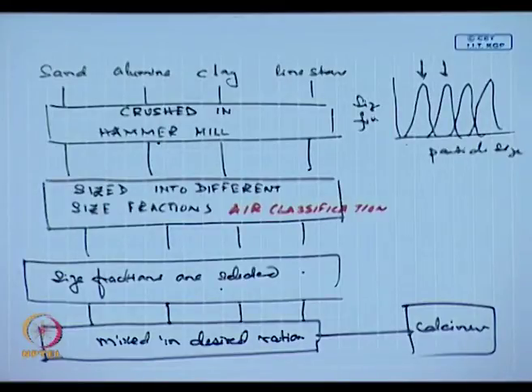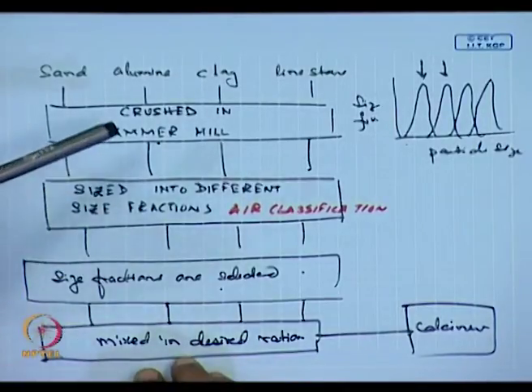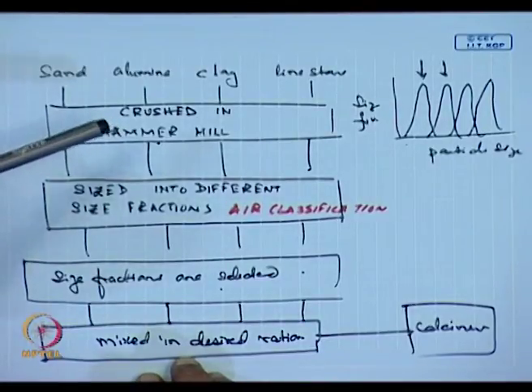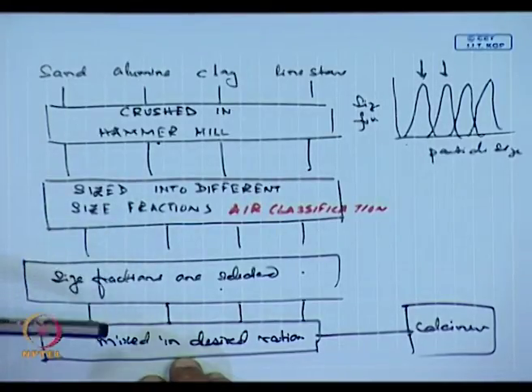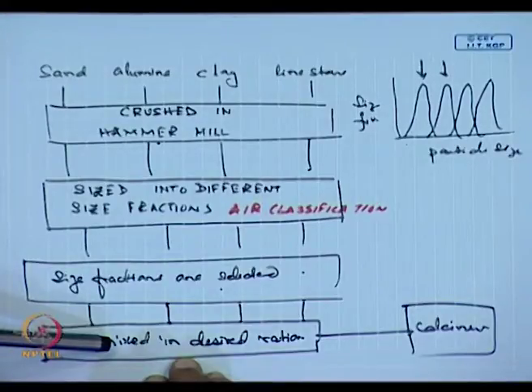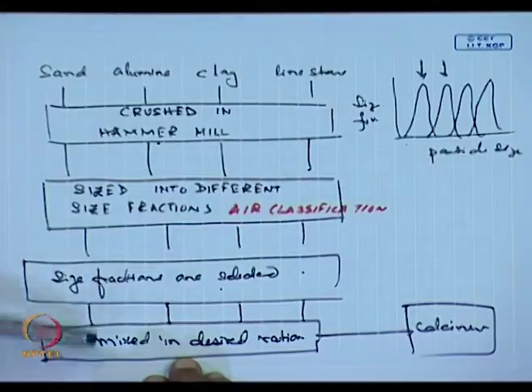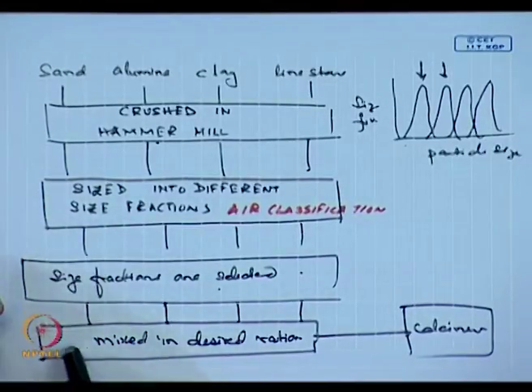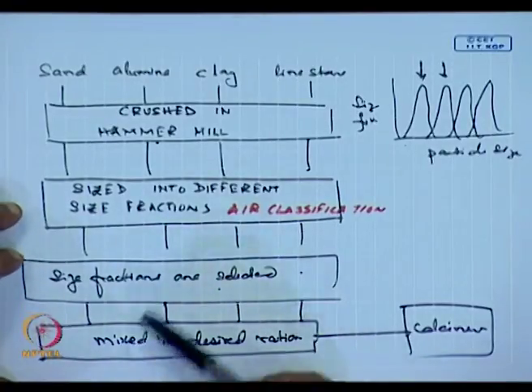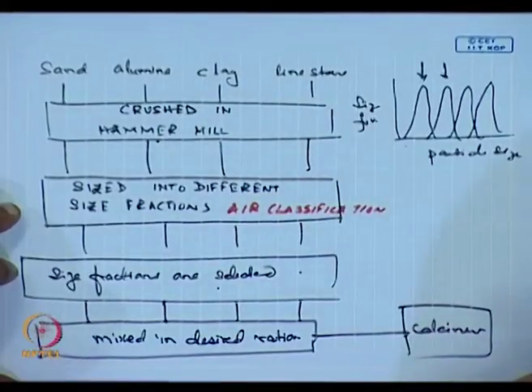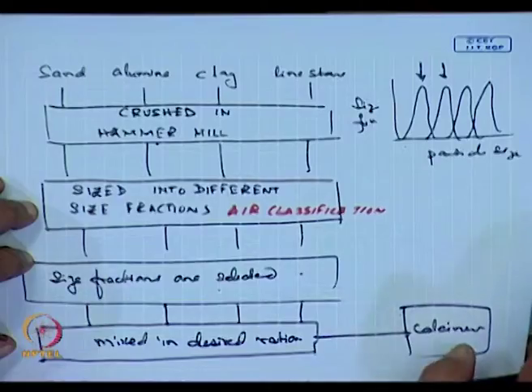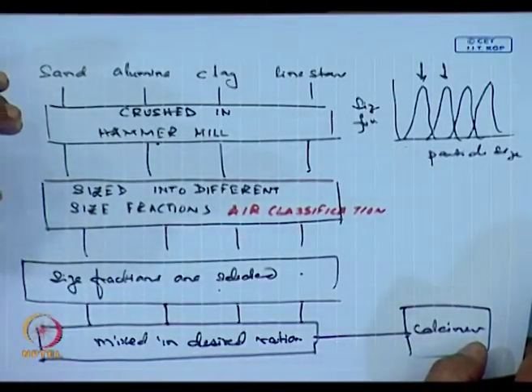The improvement in cement technology that is happening is because of a couple of things. One, these air classification equipments, size fractions are being chosen very properly. The whole thing is an assembly line fashion, and as a result, after doing the size fractions, we can vary the amount of limestone, clay, alumina, sand depending on a requirement, make sure they mix, and in the calciner we do not have big pebbles to calcine, we have very fine powders which we calcine. The best cements of today are very, very fine powders, and that is where all these dry grinding processes come in very handy.